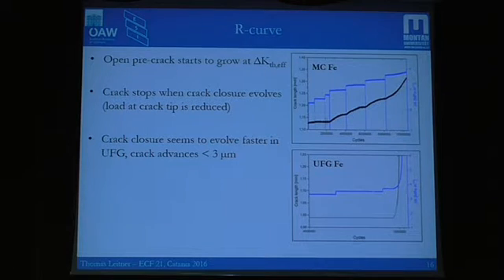Now for the ultrafine-grained iron, we don't see these steps where the crack starts to grow and stops again. So what's the reason for that? We don't think that no crack closure is active, but that we just cannot detect the small crack extension at the beginning. We have a resolution for our measurement technique of about 1 to 3 microns. So it seems that these little crack extensions are just smaller than our detection limit.